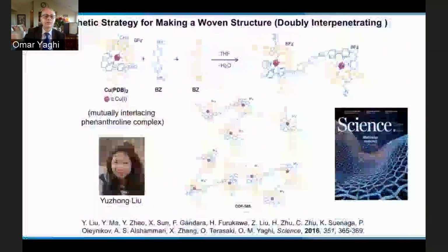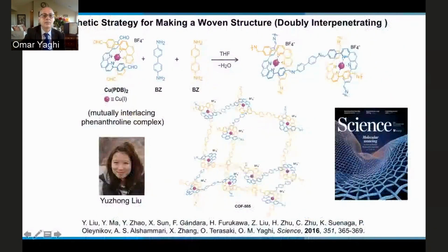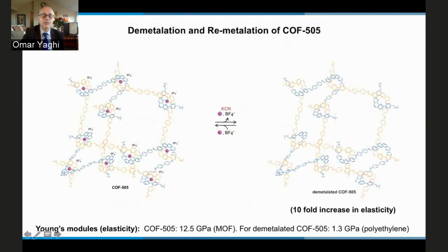So that's exactly what, in the end, Yuzhong Liu was able to do. She took this mutually embracing complex that Jean-Pierre Sauvage used to make catenanes, but instead of catenanes, she functionalized it with aldehydes and copolymerized it with the diamine to make, as you can see here, threads that are weaving in and out of each other, and brought together at regular intervals by the presence of the copper to make a woven structure.